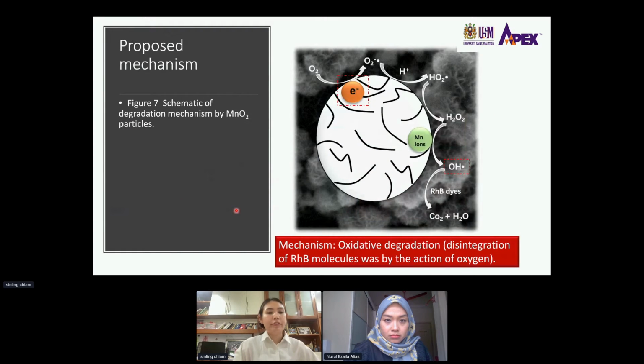So combining all the results, the mechanism of dye removal is proposed. The crystal defect in the amorphous structure of MnO2 acts as an electron donor. So the electron will react with the oxygen species through a series of oxidation processes to produce hydrogen peroxide. Then the manganese ion in MnO2 will catalyze the reaction of hydrogen peroxide to produce the hydroxyl radical.